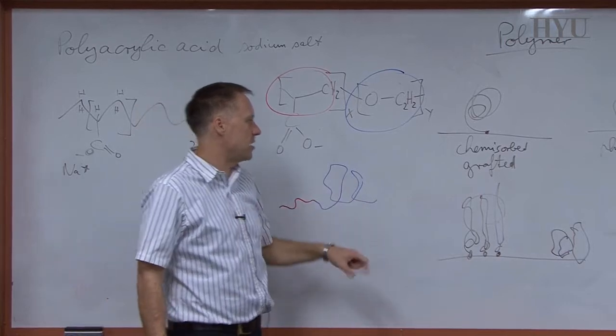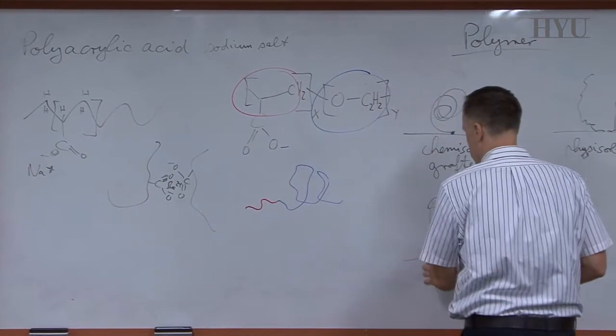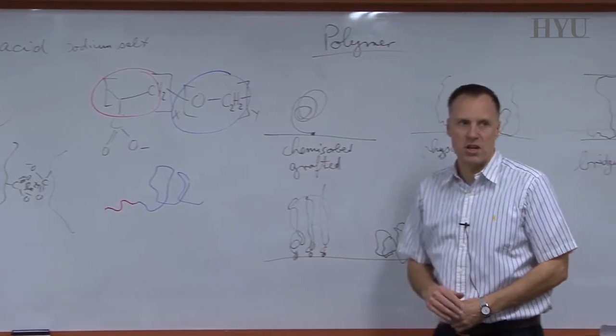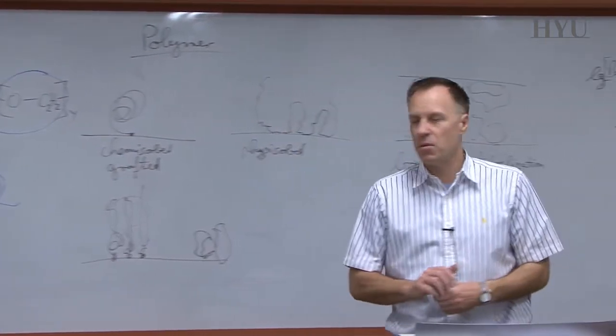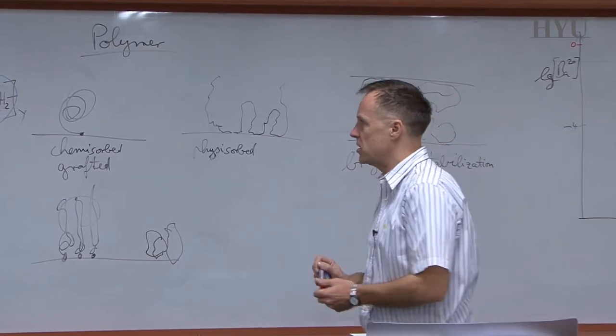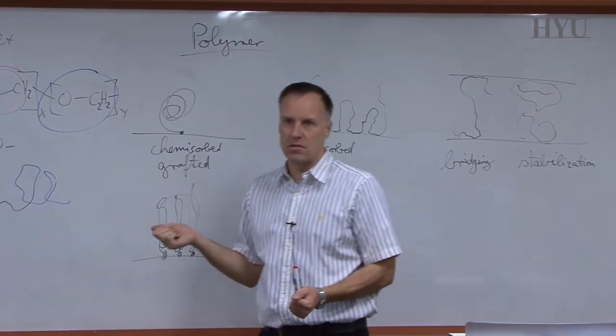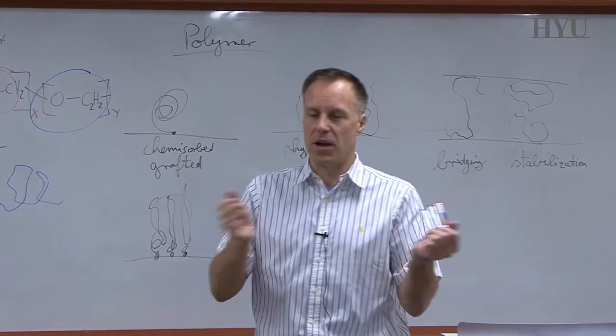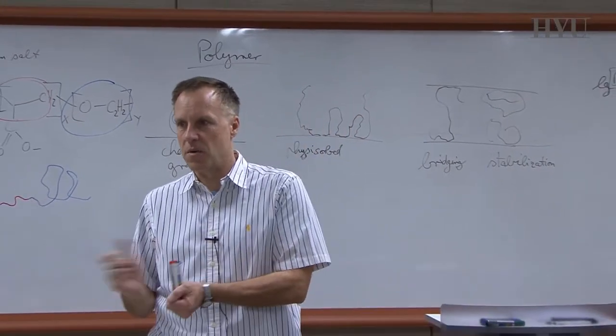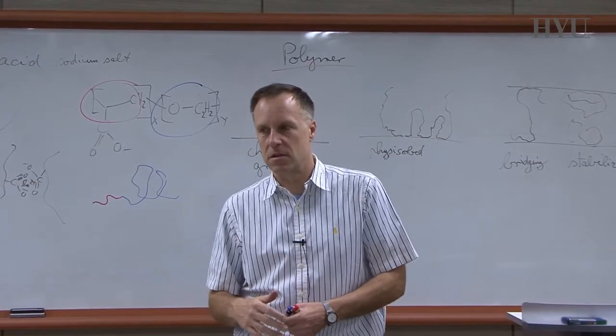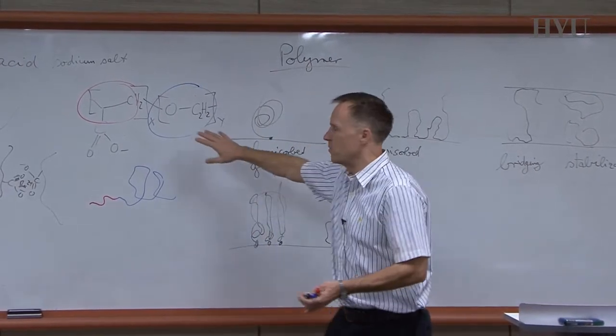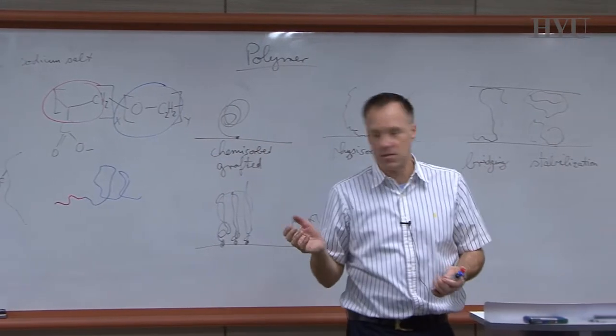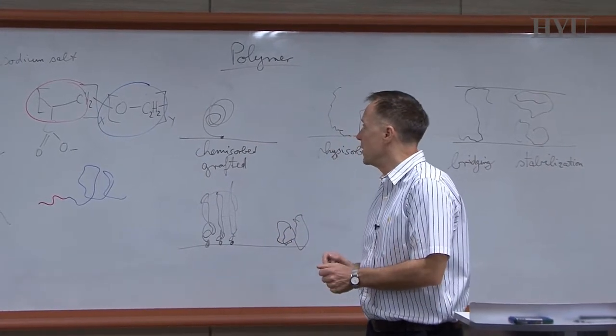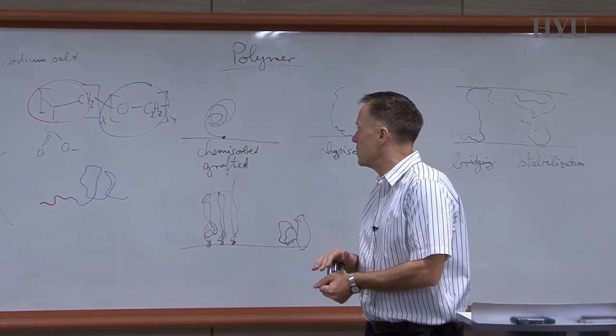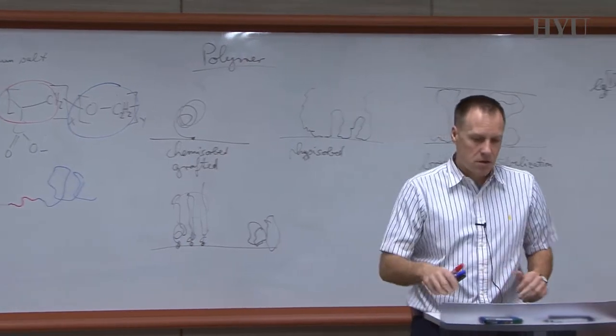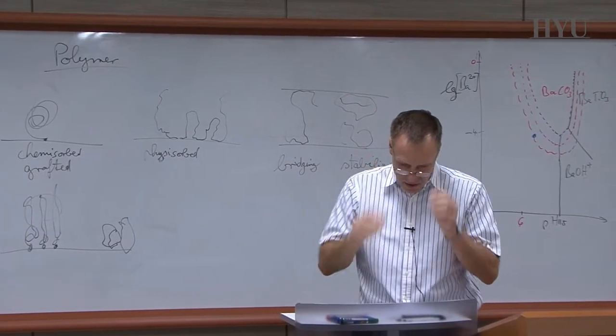And now you have basically a chain that can extend, and you have a short chain that can adsorb, and you're coming to these so-called brush-like systems. Yeah? And with this, you can form really nice dispersions of this material, and you don't have to worry about the barium ion concentration. Yeah? So by moving away from electric double layer now to polymers, we have the ability to overcome the problems in water. So these are water-soluble, obviously, these compounds. You can overcome the problems that are associated with the dissolution of barium ions. Okay, so that was this part.